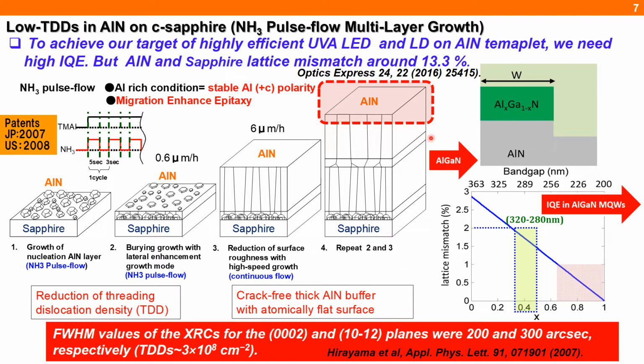The next step is to grow the AlGaN-based quantum well structure, but AlGaN and aluminum nitride have a lattice mismatch of around 2%, depending on the emission wavelength of the UVB laser. So we used a low pressure MOVPE system at Riken to grow the quantum well structure and the laser diode structure too.